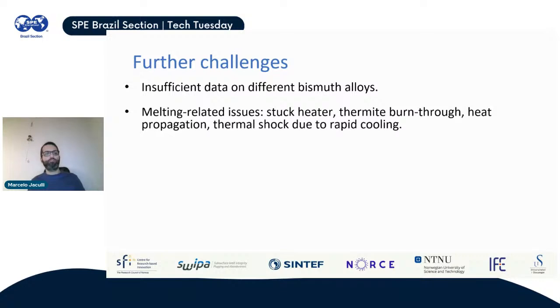There are some issues related to the melting process. You saw from the video that you are lowering a tool with the bismuth alloy, and then you are melting it, and then it falls into the well, and then it closes this annular gap. But there is the potential for this heater to be stuck there. You want to retrieve this before the alloy solidifies, but if it solidifies first, then you are probably going to have the heater stuck there. So that could be an issue. You could have a problem with the thermite if you are using, for example, a thermite technology to melt the alloy downhole. You could maybe not be able to melt everything depending on how you ignite the thermite.